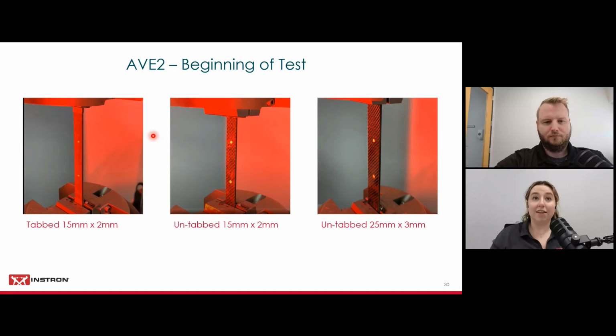Next, the AVE. What I'm showing here is my 50 millimeter gauge length that I marked with a white paint pen across all 3 of my specimens. And even though they had different surfaces, I didn't have any issues using that white paint pen to mark my gauge length onto the specimen. And I used a stencil that allowed me to place it in the proper area.